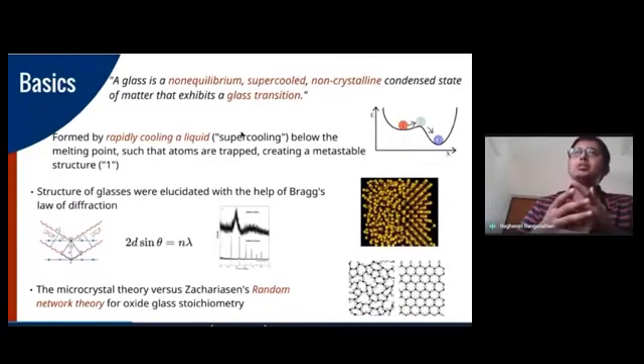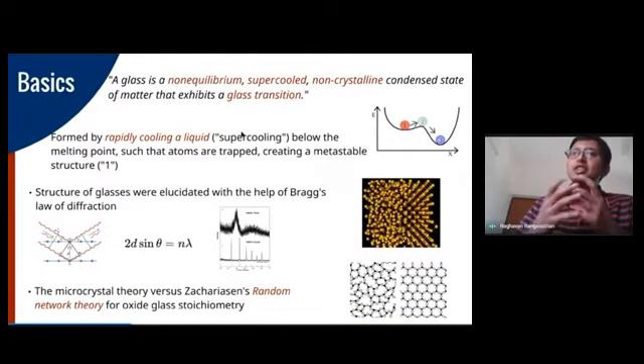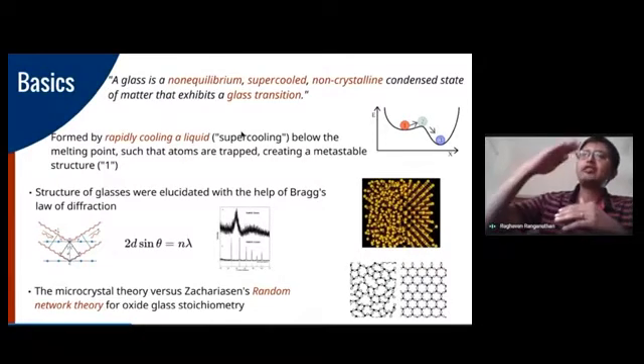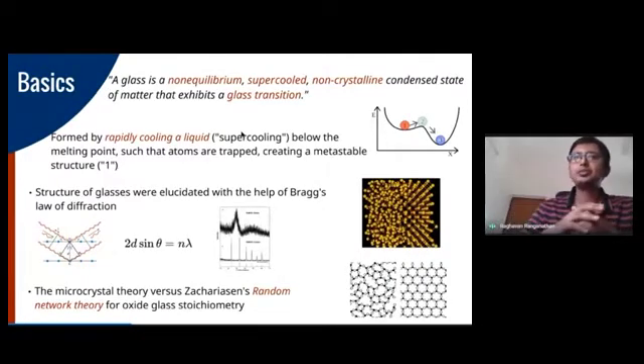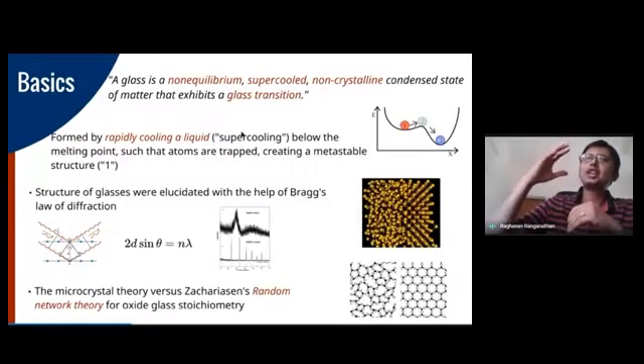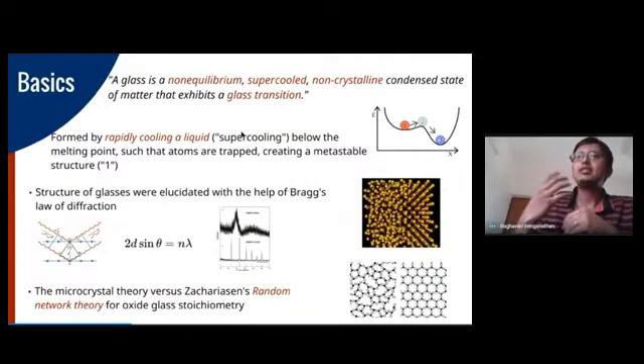So glass is clearly not an equilibrium structure. In fact, it is a structure that's formed by rapidly cooling the liquid. Okay? And that's what we mean by supercooling, where the word super basically indicates that you need a reference state below which you need to cool the glass to. So to reiterate, we have a liquid structure and we want to create a glass out of it. The way we do it is by supercooling the liquid, meaning we cool the liquid below the melting point of the liquid. And what this does is essentially trap all the atoms in a metastable structure.